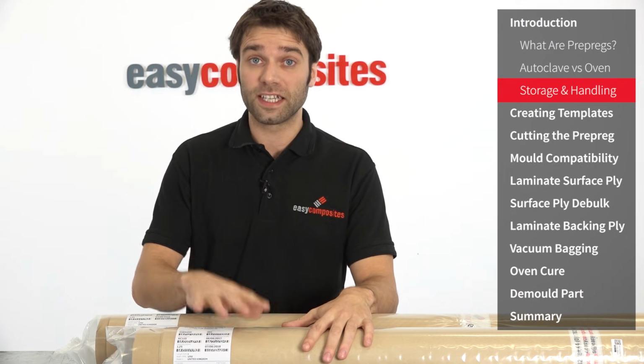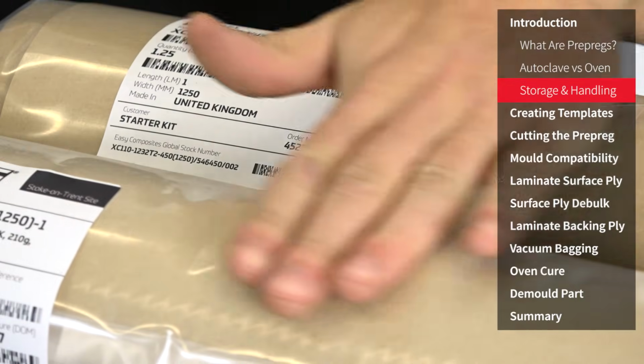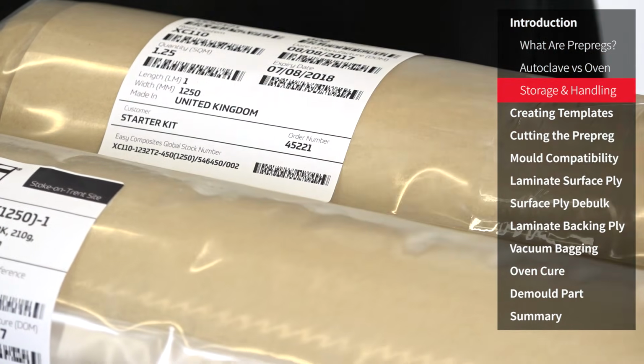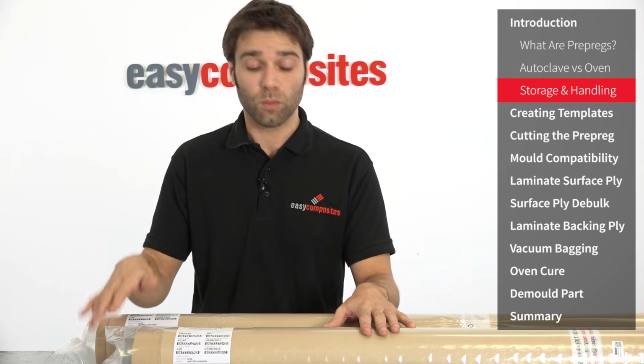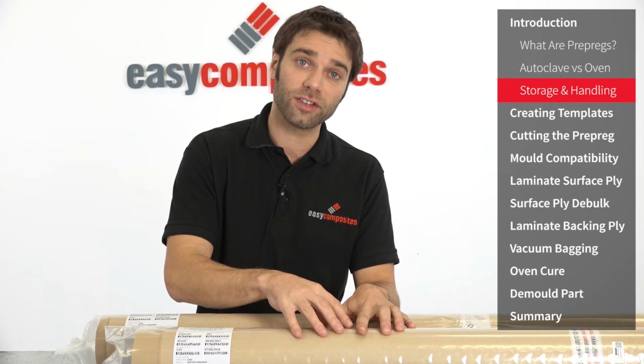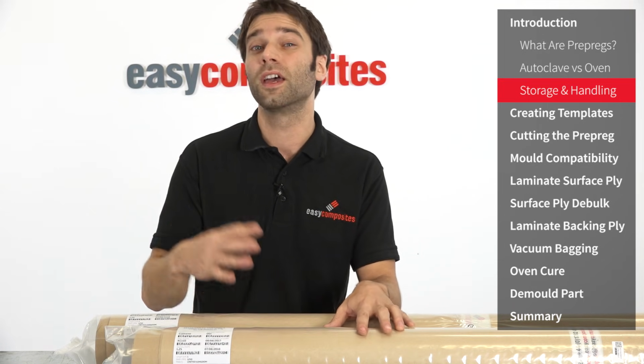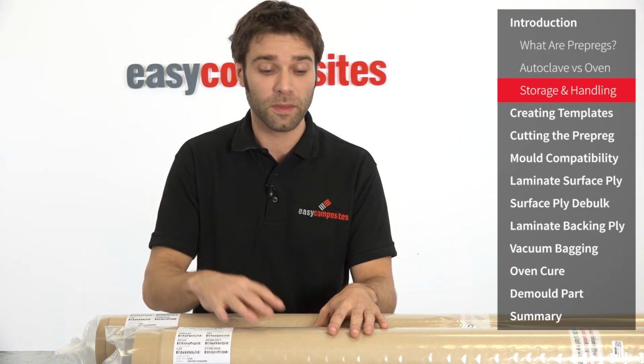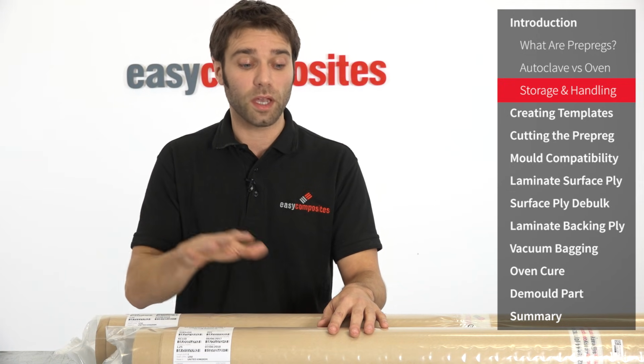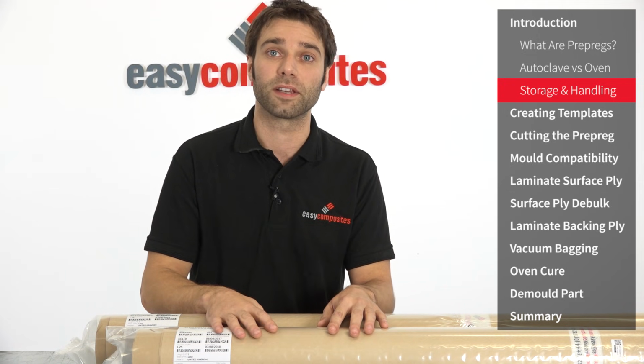but it just shows that the resin's always curing even at room temperature. The rolls that we got out of the freezer earlier are still defrosting, and you can see the condensation forming on the surface. This is the reason why they must be kept in sealed packaging while defrosting. Otherwise, that condensation could form on the roll itself and potentially contaminate the material. So while these are defrosting, we're going to crack on and start out with the templating.